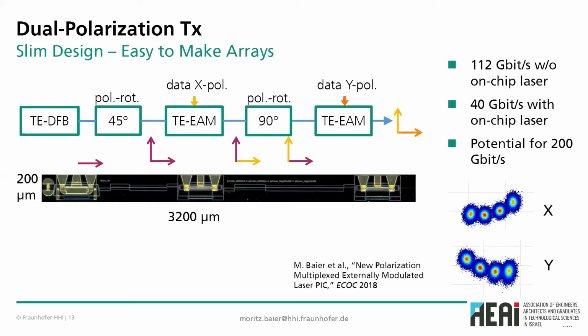Another example leveraging the aforementioned polarization rotators is this dual polarization transmitter, where we use a DFB laser that emits only in the TE polarization, which, as I mentioned earlier, normally can be perceived as a limitation because everything is strongly polarization dependent. But here we use a 45-degree polarization rotator to effectively convert 50% of the TE polarization into TM. That's shown by those 2 purple arrows here. And now we have an electro-absorption modulator, which also only affects TE polarization. So the yellow data signal that you apply to this modulator will be imprinted onto only 50% of the optical carrier, namely the TE polarization.